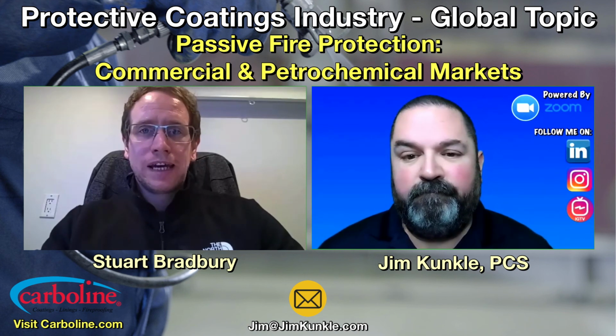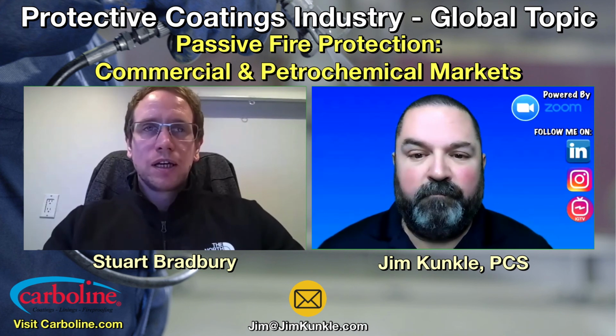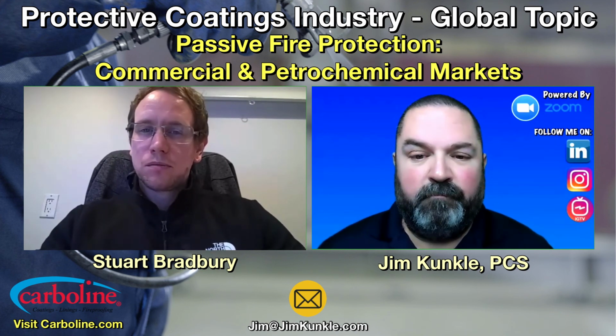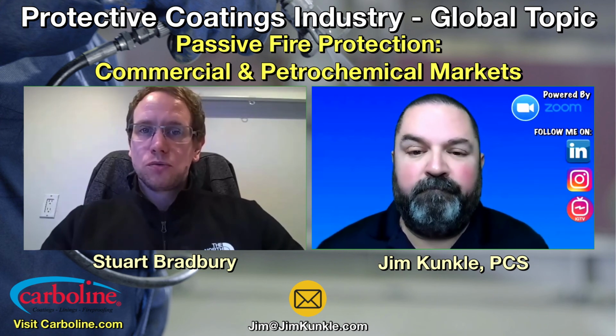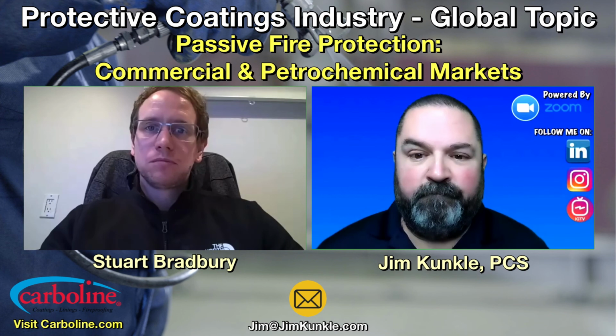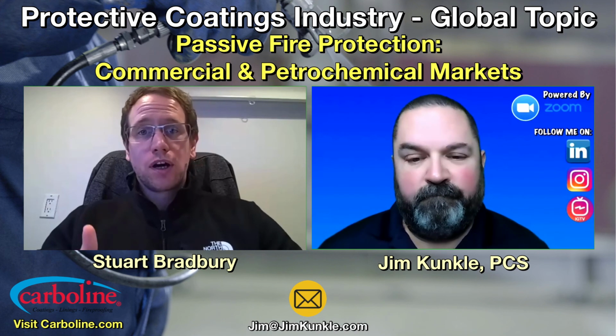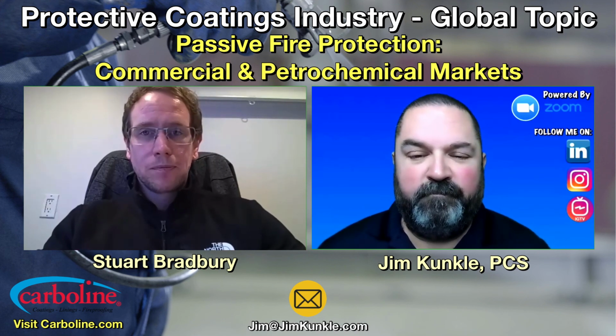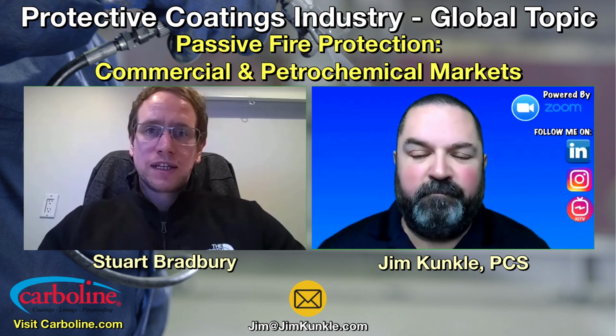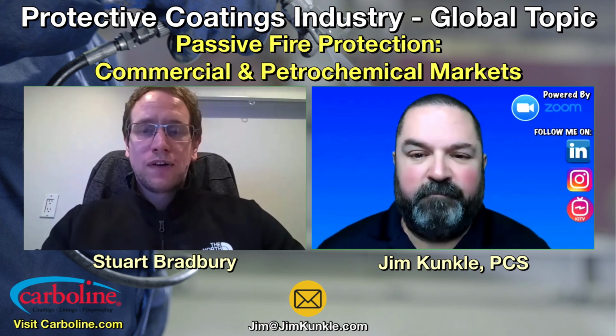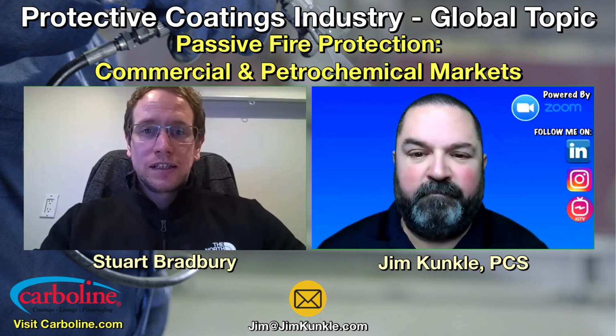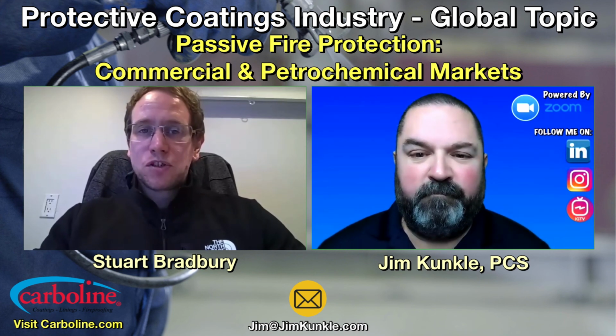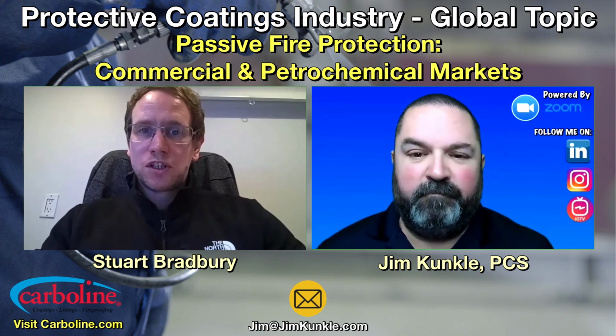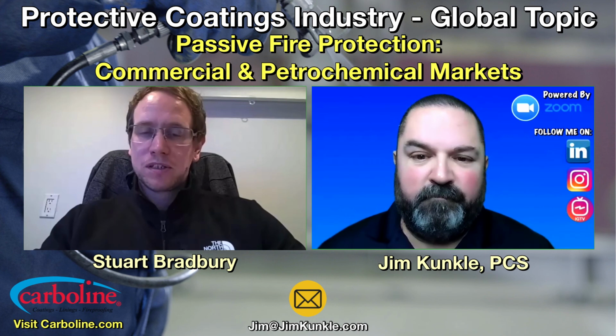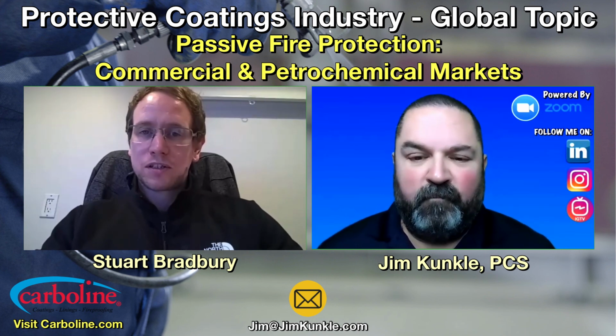And the application of an intumescent paint or cementitious material would provide short-term thermal protection by insulating those steel sections through either char development or steam layer, dependent on the material type, which slows the temperature rise in the underlying steel section for a given period of resistance. So I think it's important to understand that within 5 minutes of either a cellulosic fire and certainly a hydrocarbon fire, the temperature rise is almost at the point where steel would lose its yield strength. In 5 minutes. So I think that's key for your subscribers to understand.